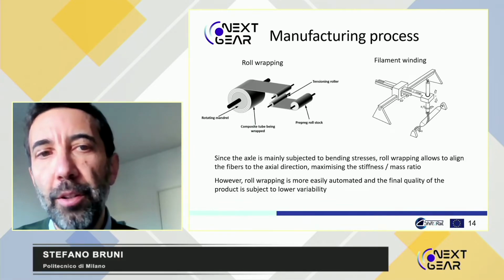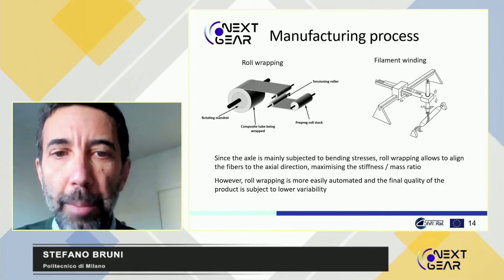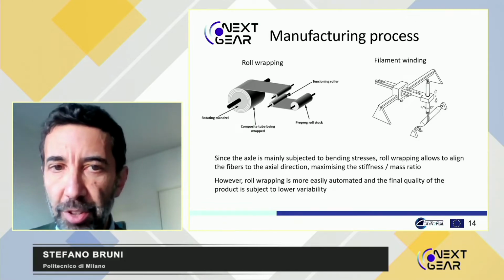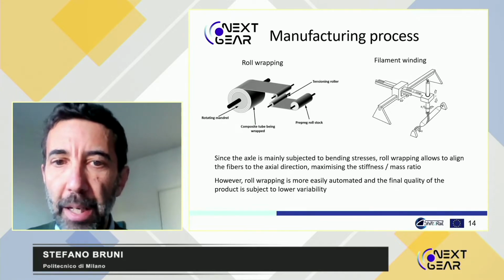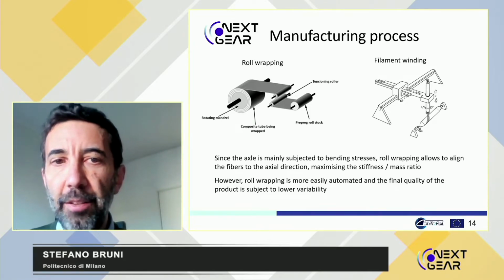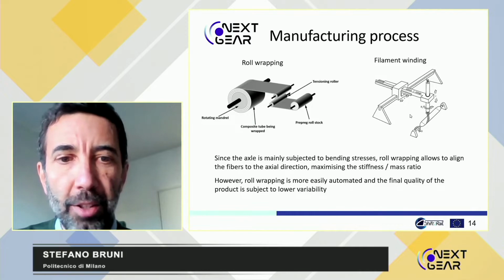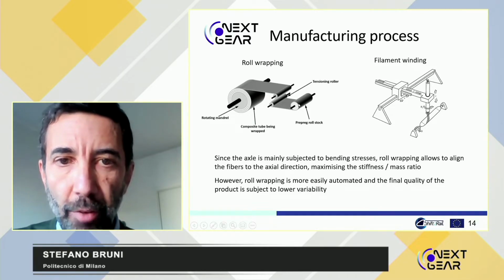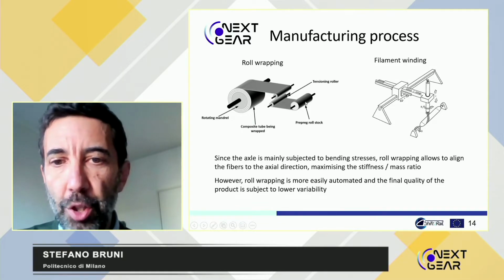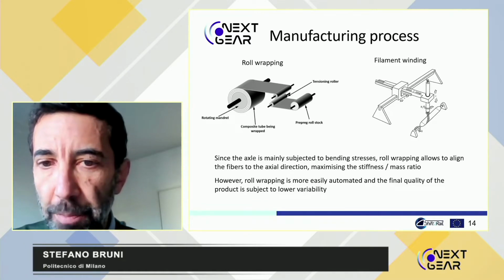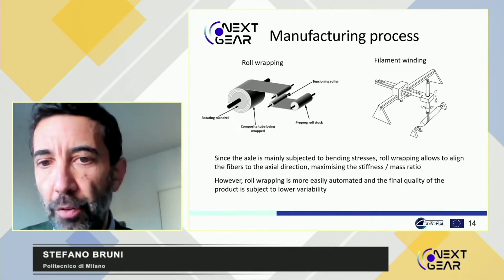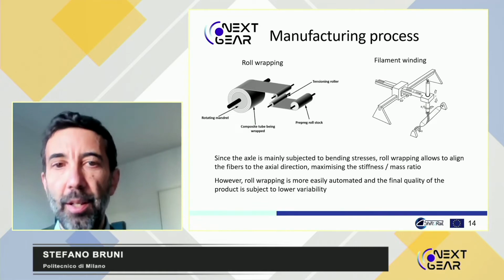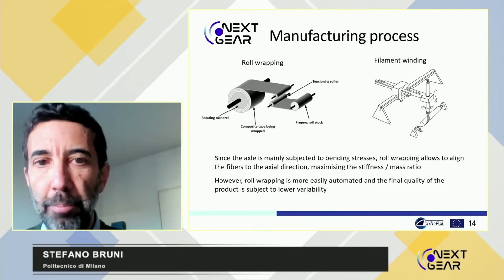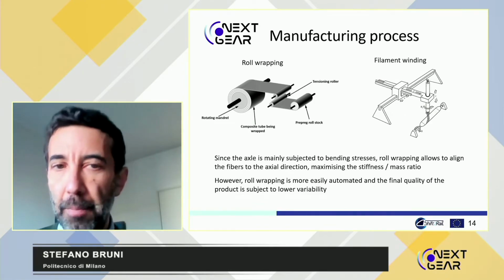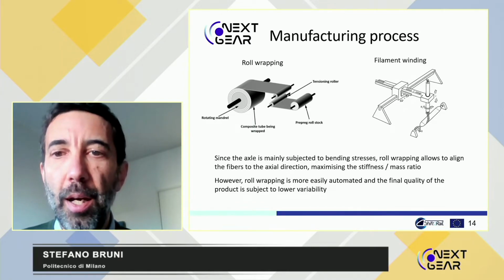The benefit, the nice point with roll wrapping, is that because the stresses in the composite tube are mainly due to bending, roll wrapping allows aligning the fibers in the axial direction for the tube, which means there is a chance to maximize the stiffness over mass ratio. So you get the highest stiffness for a given mass of the tube, I mean bending stiffness.